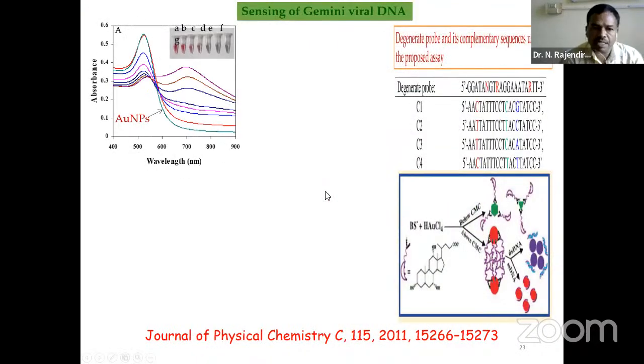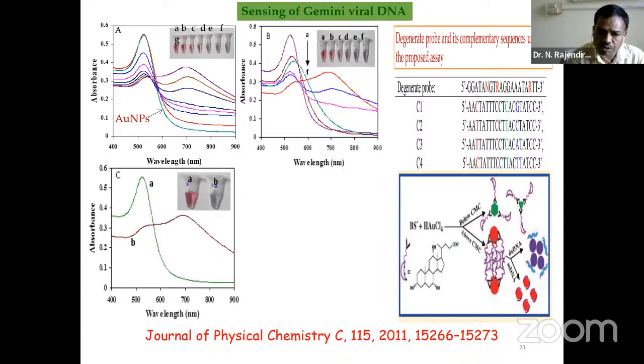And after the reduction, after the optimization we used this solution for the detection of geminiviral DNA using a colorimetric technique. That is because these nanoparticles are very sensitive to analytes. If you add any interfering ions and other things, the color will change. So using these advantages, we use it as a colorimetric probe for the detection of geminiviral DNA. Normally, instead of going for PCR and other costly equipment, just colorimetrically we can identify how much the single stranded DNA probe is getting sequenced.